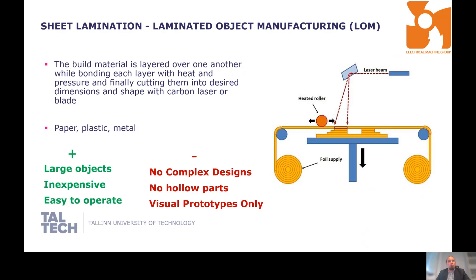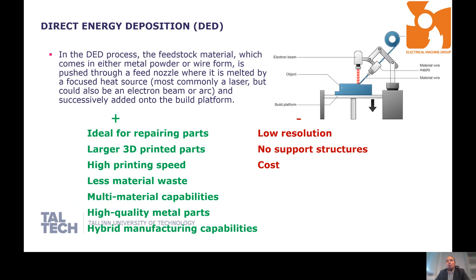Then we have direct energy deposition, or DED. This is basically similar to electrical welding — material wire comes onto the bed, and with an electron beam or laser we melt it, building up layer by layer. It is very good for repairing parts or producing large 3D printed parts. The problem is that it doesn't give very good resolution — you can't produce very thin-walled systems — and at the moment it's quite a costly printer.